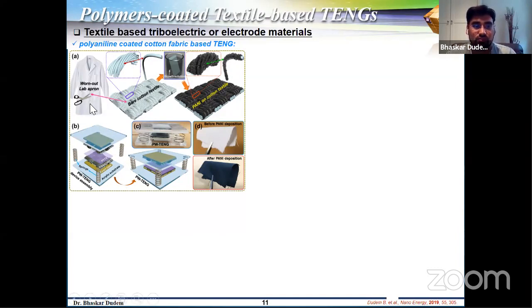We used a worn-out lab coat, diced and cut it into pieces, and further grew some conducting polymer on top of this textile. By using a simple technique like dipping into the polymerization solution and letting it grow for 20 hours, it grows very easily at very low temperatures. And this textile is further used to make the triboelectric nanogenerators. It is even washable and mechanically sustainable too. What we did is, one textile is used as a top triboelectric material, and it's used as an electrode as well as the triboelectric material.